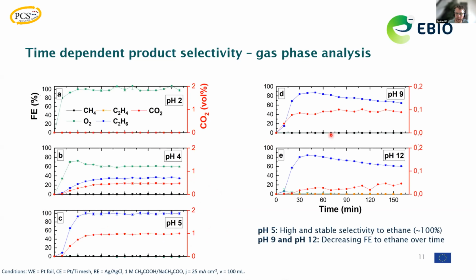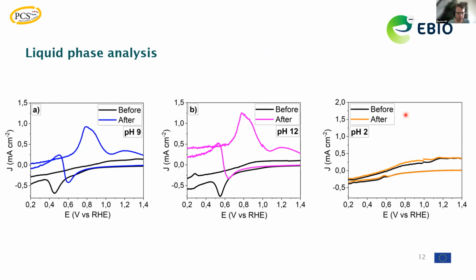If we then go to the higher pHs of pH 9 and pH 12, we observed again a quite high Faradaic efficiency for ethane initially, but we also realized that there's a drop in ethane selectivity, but we couldn't detect any oxygen, which is an indication that, of course, after a certain period of time, the reaction mechanism might change from Kolbe processes to non-Kolbe processes. And what is also clearly shown here in these time traces is that the CO2 evolution at higher pHs is even smaller compared to the intermediate pH regime of 5. And what this means, I will tell you in a moment.